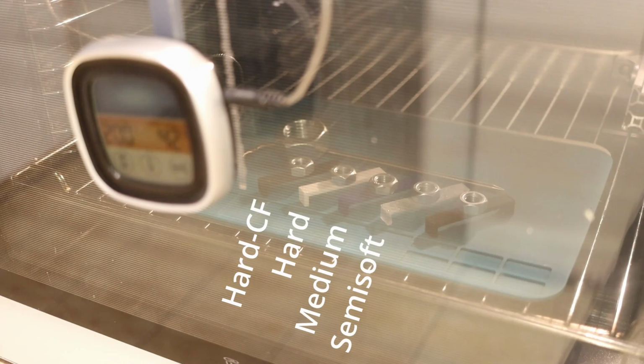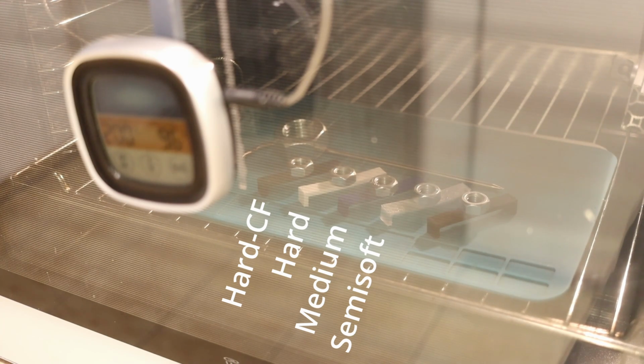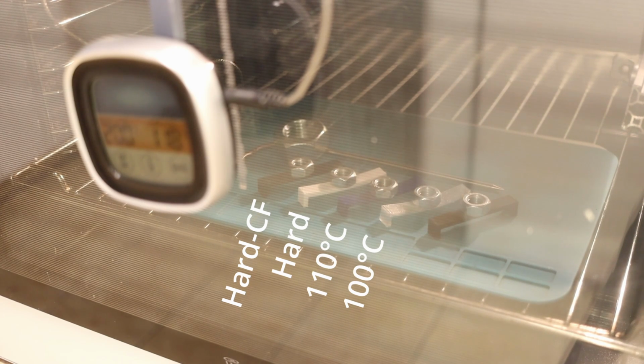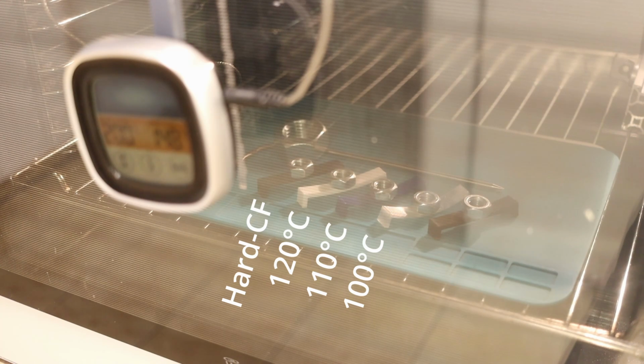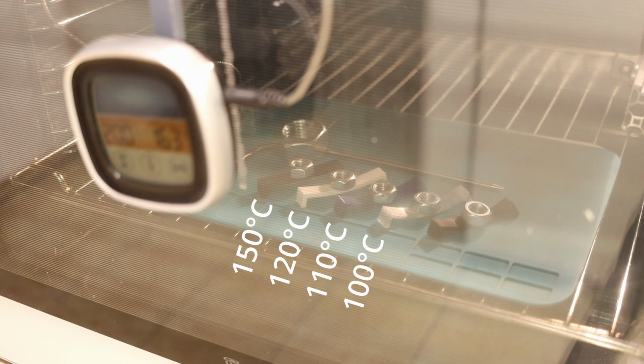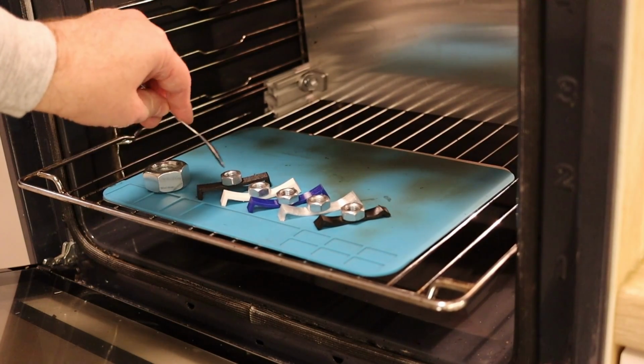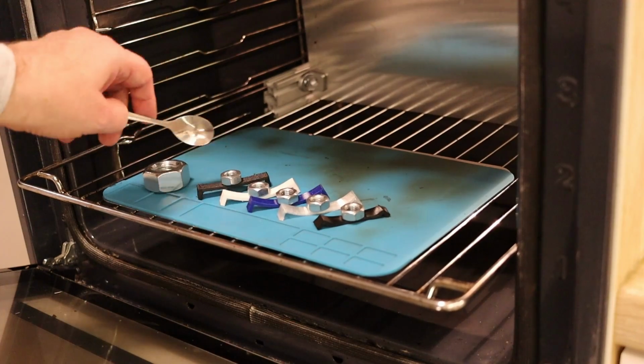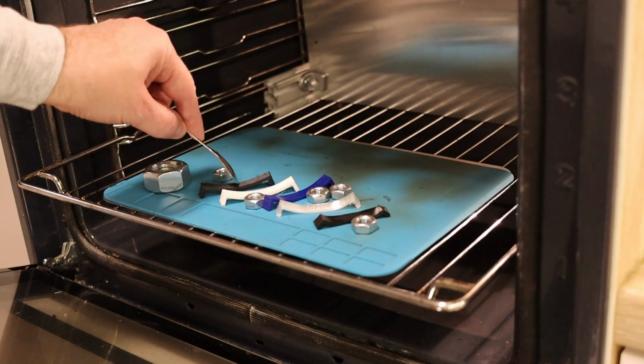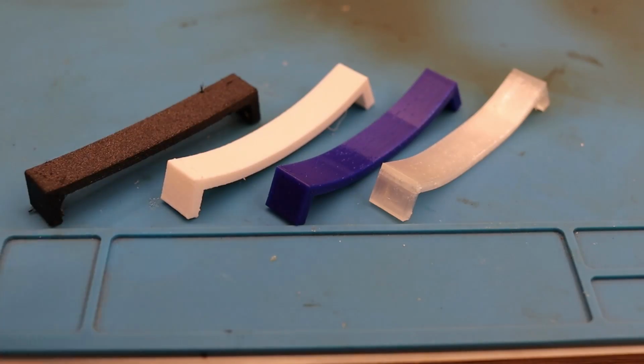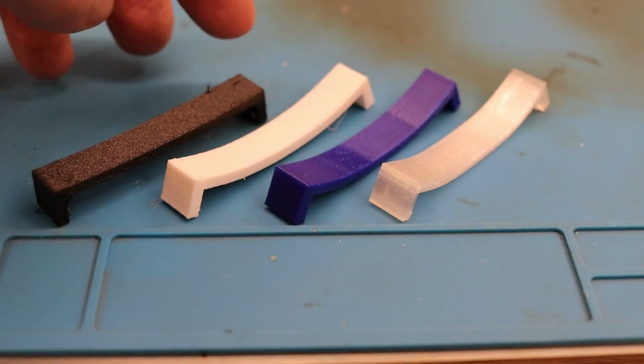At the beginning no changes, and then the first deformation I noticed on the semi-soft filament, then on the medium, hard, and on the carbon fiber version I noticed the first deformation only at approximately 150 degrees Celsius, but even then the deformation was very minimal. And basically this is very similar to the given specifications by the extruder. So I can see some elasticity on each of them. And only after 2 minutes they all get back their own flexibility.